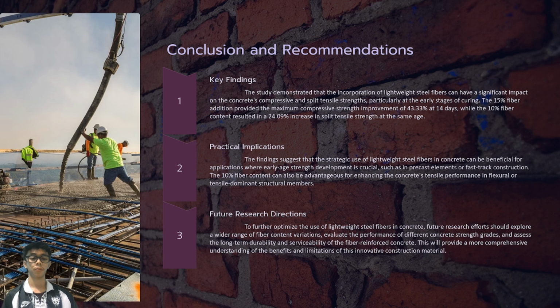Conclusion and recommendation. First, key findings. The study demonstrated that the incorporation of lightweight steel fiber can have a significant impact on the concrete compressive and split tensile strength, particularly at the early stage of curing. The 15% fiber addition provided the maximum compressive strength improvement of 43.33% at 14 days, while the 10% fiber content resulted in a 24.09% increase in split tensile strength at the same age.